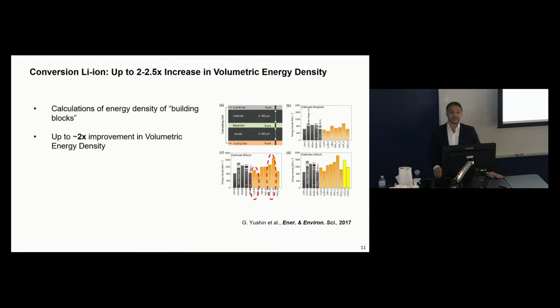I mentioned that the performance of this new chemistry can be higher, and the cost can be lower. How can I say that? Well, if you look at lithium-ion batteries, depending on the configuration, it can be cylindrical, prismatic, or pouch type, but if you open it up, you will see it consists of the same building blocks, right? You have a current collector, aluminum for the cathode, copper for the anode. You have electrodes, so anodes and cathodes with active material and some porosity, because everything is immersed in electrolyte, and so lithium ions propagate through the electrolyte. And then there is a separator that electrically separates the anode from the cathode.